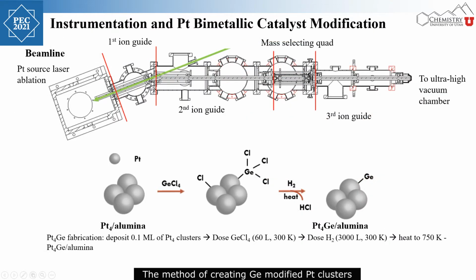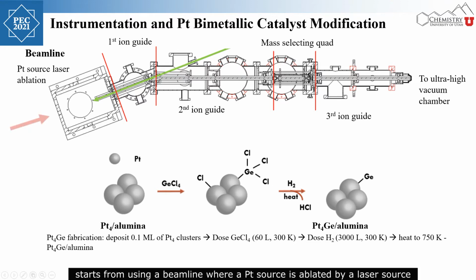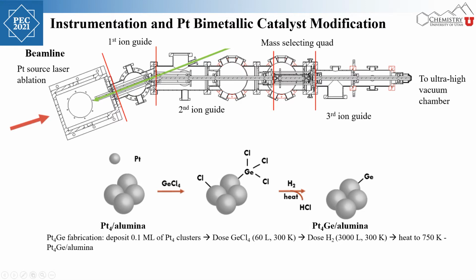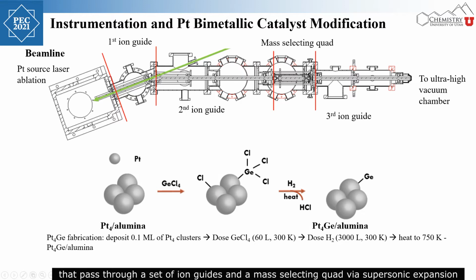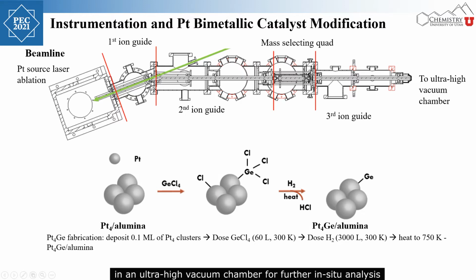The method of creating germanium-modified platinum clusters starts from using a beamline, where a platinum source is ablated by a laser source. The laser ablation creates a mixture of platinum ions that pass through a set of ion guides and a mass-selective quadrupole via supersonic expansion to an alumina support in an ultra-high vacuum chamber for further in-situ analysis.